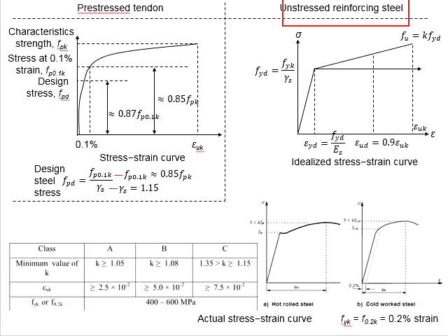As for the typical reinforcing steel bar, the design yield strength will be determined by FYK divided by its steel factor of safety. The factor of safety is 1.15. Based on the idealized stress-strain curve, the ultimate strength of the reinforcing steel bar will be a factor of K times its design strength. This factor K can be referred to the table here, which separates it into class A, B, and C. And the ultimate strain epsilon UK is also given here.